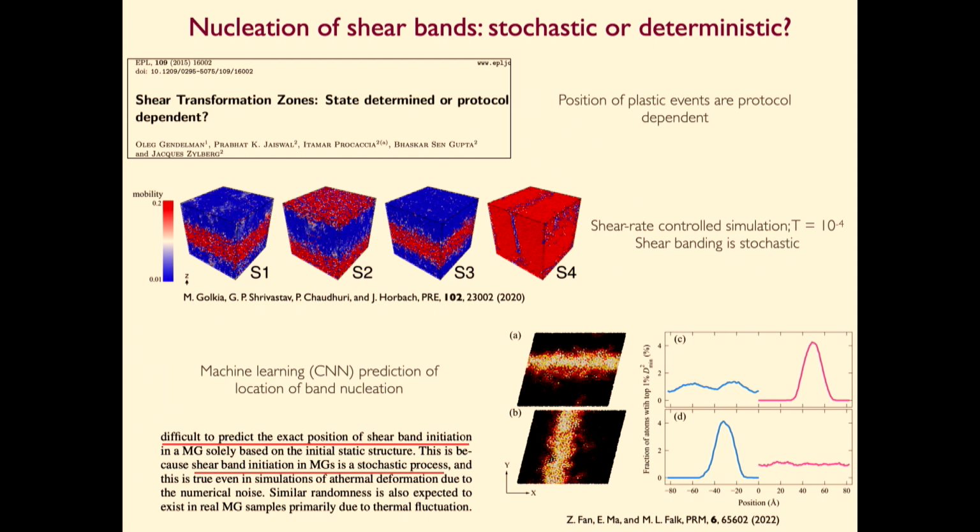Similarly, in this particular study by Pinaki, Jürgen and others, they have shown that in a binary Lennard-Jones mixture at very small temperature, this shear banding is completely stochastic. They start with the same initial configuration of the material, and they change the thermal noise by changing the seed of the thermostat, and they see that these band patterns completely change in different deformations, starting with the same